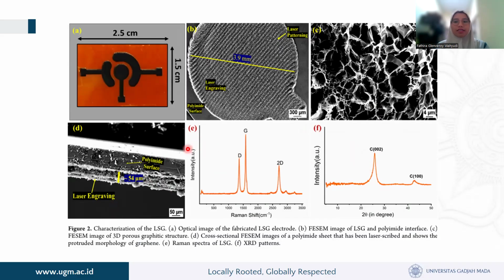The structural analysis is shown in figures 2E and 2F. 2E is the Raman spectrum, which displays D, G, and 2D peaks, indicating the formation of a graphitic structure with defects and sp2 domains characteristic of graphene. Figure 2F is the XRD pattern, which shows peaks at C(002) and C(100), confirming the presence of structured graphitic layers. Significance: the laser scribing process successfully converts polyimide into conductive porous graphene. The 3D porous structure increases the active surface area for electrochemical reactions. Raman and XRD confirm that LSG possesses graphene-like properties, making it ideal for sensitive and stable biosensor applications.